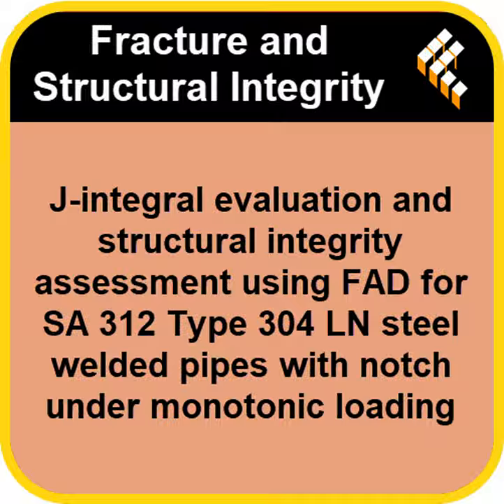A structure fails fundamentally in one of two ways. Either it kind of bends and collapses plastically. Plastic collapse. Right. Or it just snaps suddenly, brittle fracture. The FAD is designed to combine the assessment of both those failure modes. That's absolutely right. So the FAD plot itself defines an acceptable region of safety, and that region is bounded by something called the failure assessment line, or FAL.